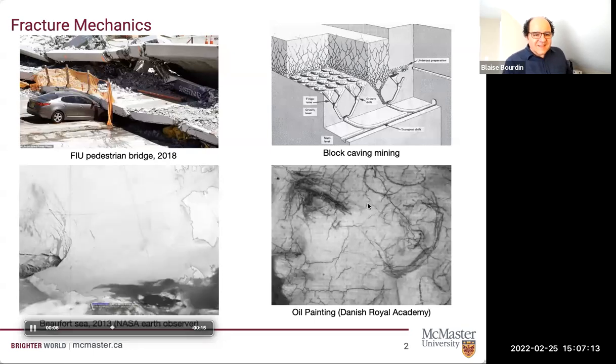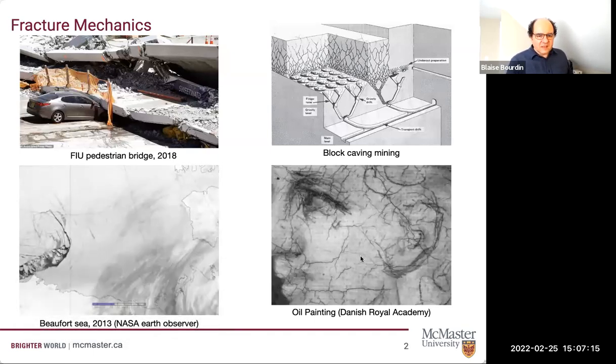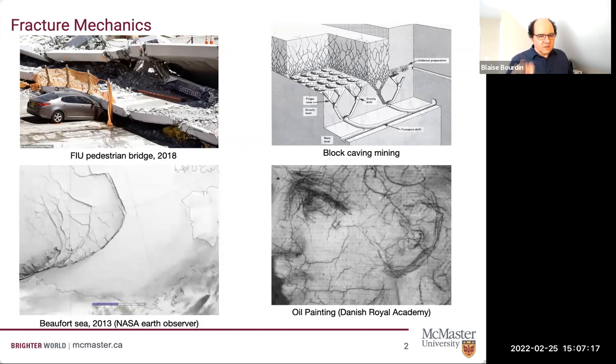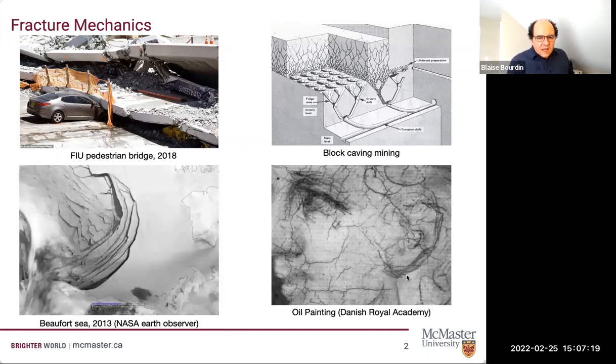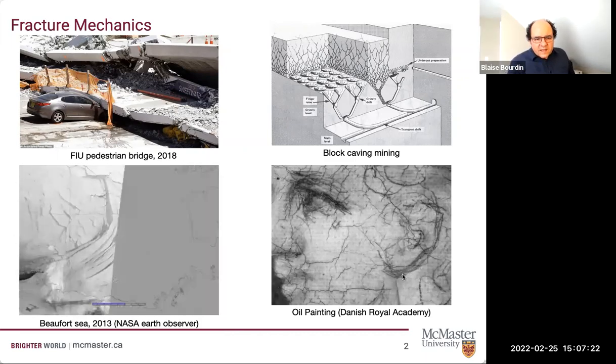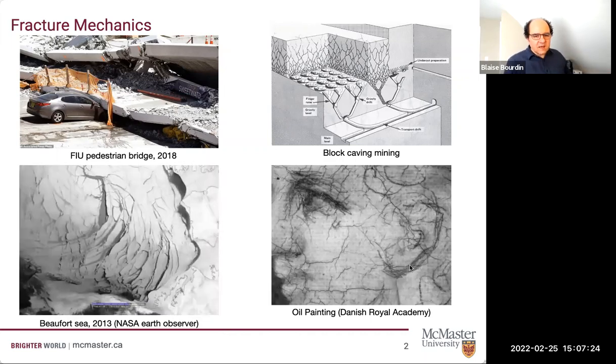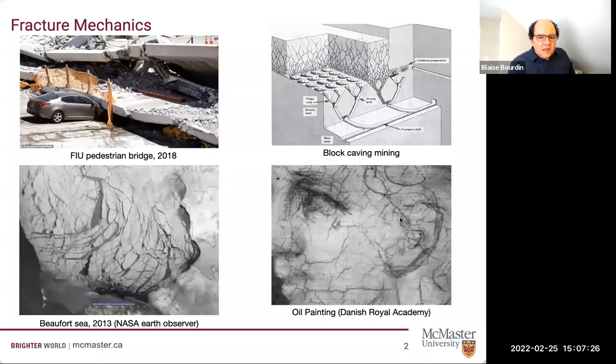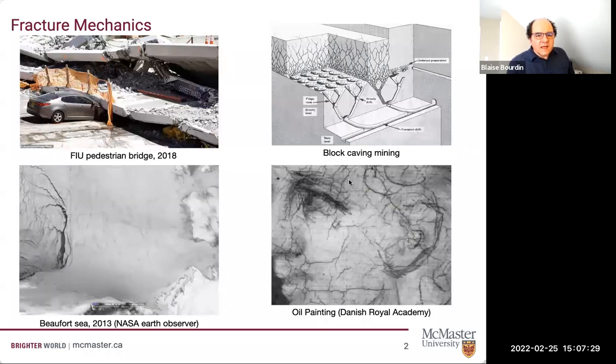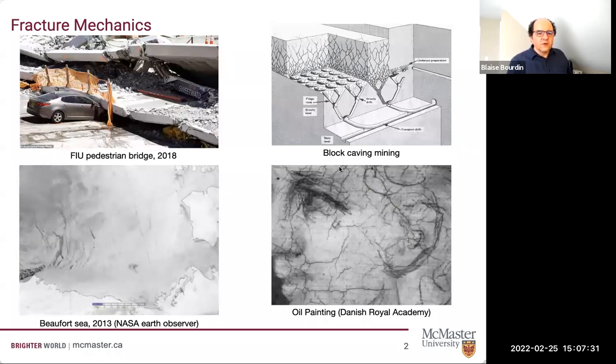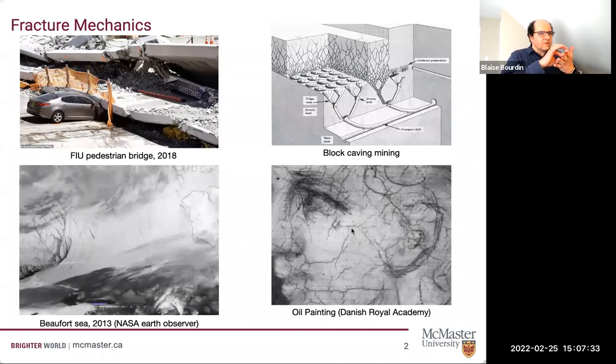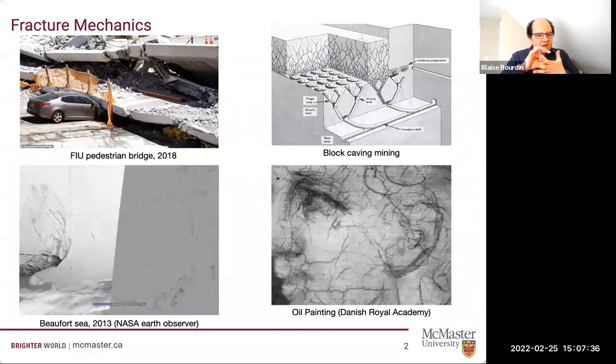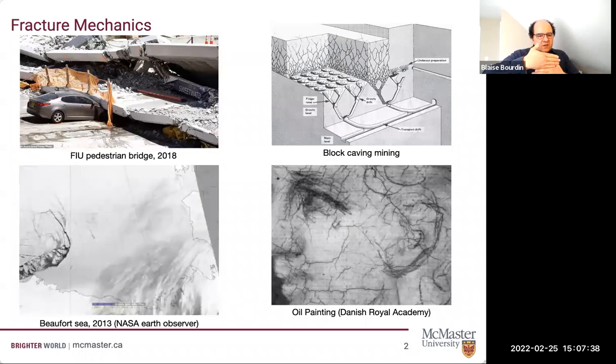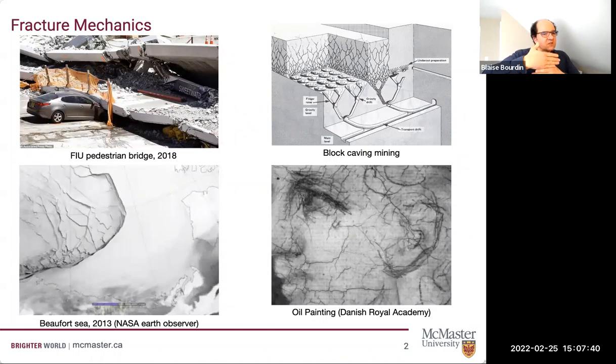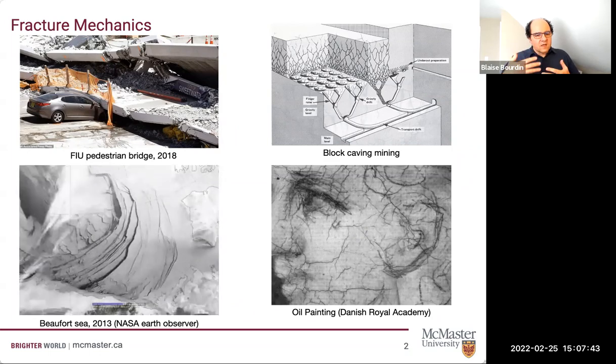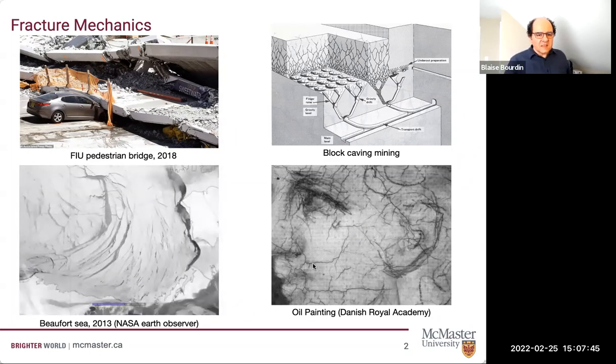Bottom right is an oil painting. So it's an infrared picture of a detail of an oil painting. And so you see these wide gray lines. These are the artist's sketch. That's not what I'm interested in. But you see these thin black lines, and these black lines are these craquelure patterns. So there's this fracture of the paint itself, and they're caused by the fact that the substrate, the canvas, stretches at a different rate than the painting itself.